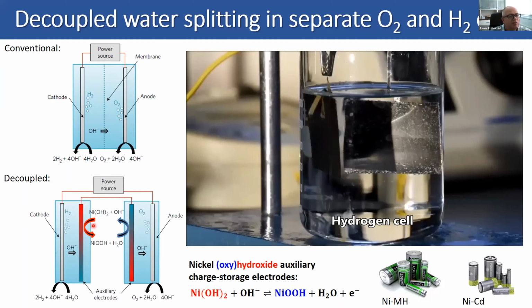The way we do it is introducing additional 2 electrodes. We call them auxiliary electrodes. They're made of the redox system nickel hydroxide, oxyhydroxide. So that's nickel hydroxide. You can charge it and convert it into nickel oxyhydroxide. And so this is the reaction that occurs at one of the electrodes. The electrode in the hydrogen cell is getting charged, while the counter electrode at the oxygen cell is getting discharged. So you have a limited capacity, you can charge until the capacity is over, and then you have to swap them between one cell to another.